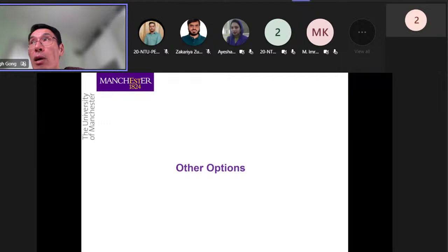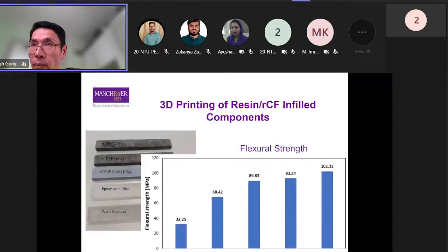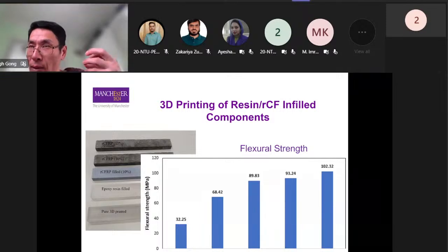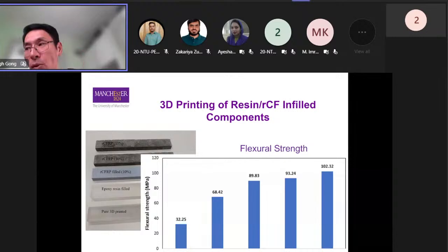Now we are also exploring other options. Some we have, some we are trying. As I said earlier, during the process of using recycled carbon fibers, we realized there is a lot of dust material being generated. One of the ideas is, can we actually use those dust materials, the carbon dust? So we try to use that to produce compound yarns or compound filaments. In this case, we use polypropylene with these dust materials as a filled 3D printed material. Originally you can print a solid material, or use a resin-filled one, or you can use RCF plus the resin and then fill it up.